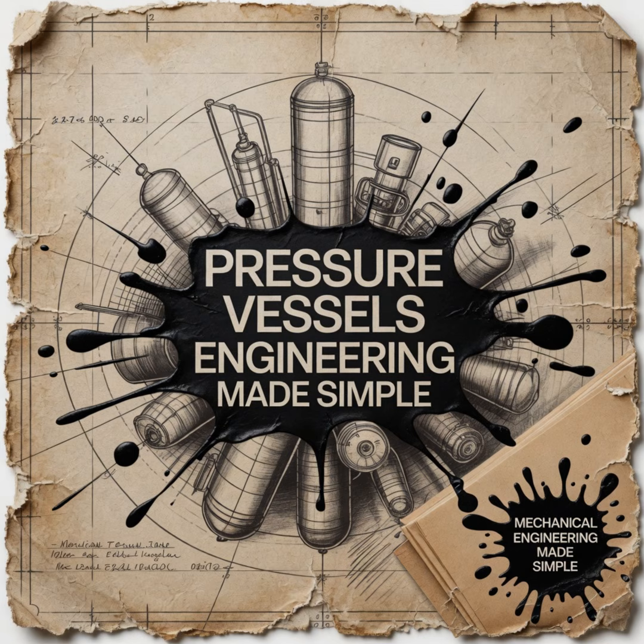A hydro test is not a fatigue test, and it is absolutely not a substitute for NDE. Because it doesn't cycle. Right. A critical lack of fusion defect might easily survive a single slow static load during a hydro test, only to propagate and fail catastrophically 6 months later under cyclic thermal loading in the field. The hydro test is the final verification, not a diagnostic tool. Well said. And the choice of the test medium is literally a matter of life and death.